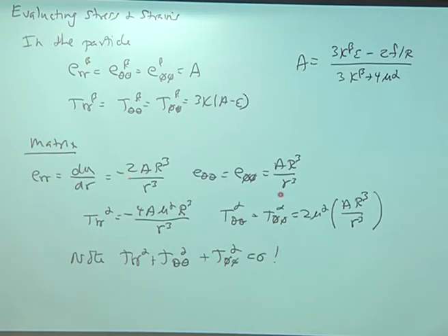Yeah. So let me step back. Basically, I wanted to write these out, and this is just algebra once we get to this point, and talk about some of the physics of this. You can see that the stress field falls off like 1 over r cubed from the particle. So it falls off reasonably quickly. It's not like 1 over r, not like a long-range Coulombic decay.